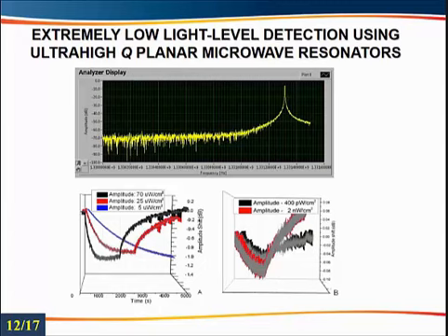But what this showed us is that traps, which abound in all of these nanomaterials and are generally viewed with distaste as a pestilence in optoelectronic devices such as solar cells and light emitting diodes, can actually be a positive from the viewpoint of sensors, especially when you have long-lived charge separated states and electrons and holes filling deep electron traps and deep hole traps.